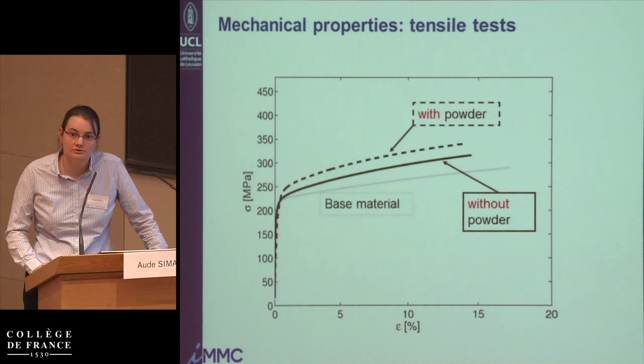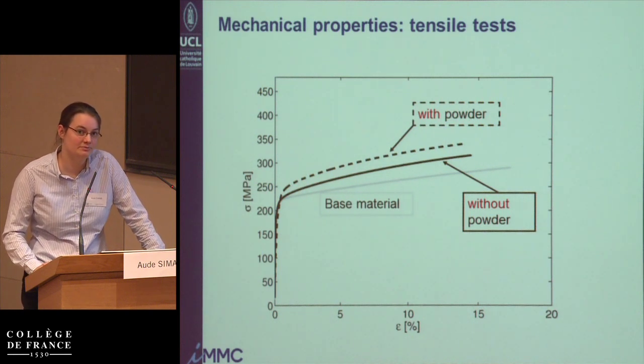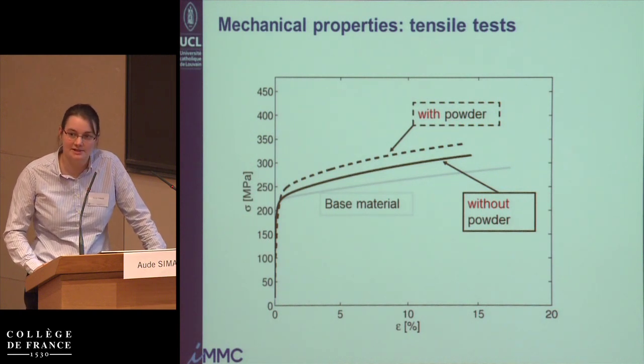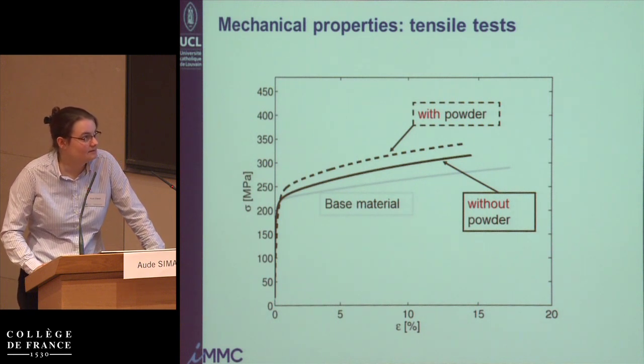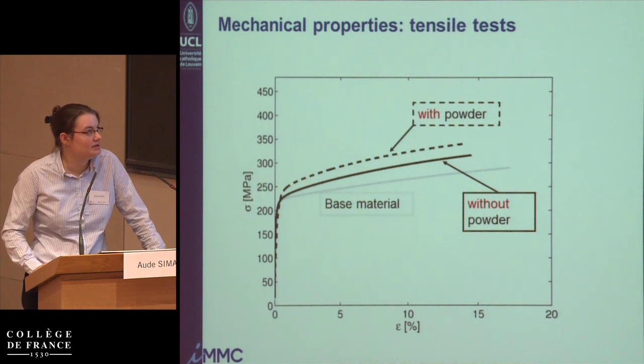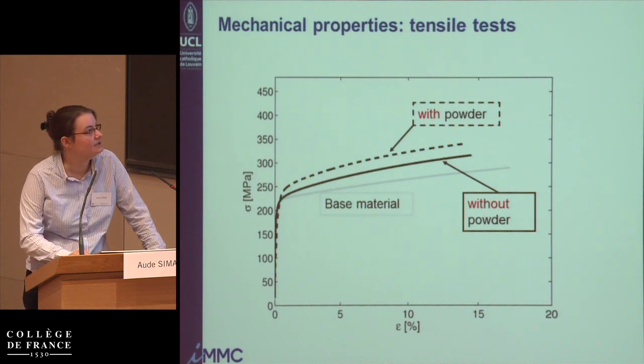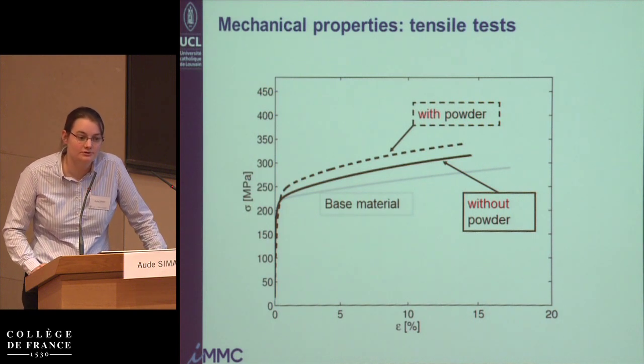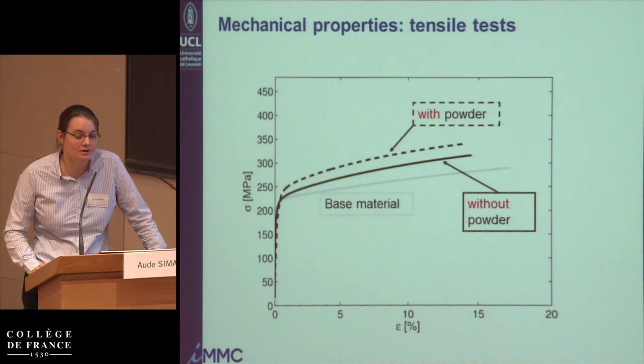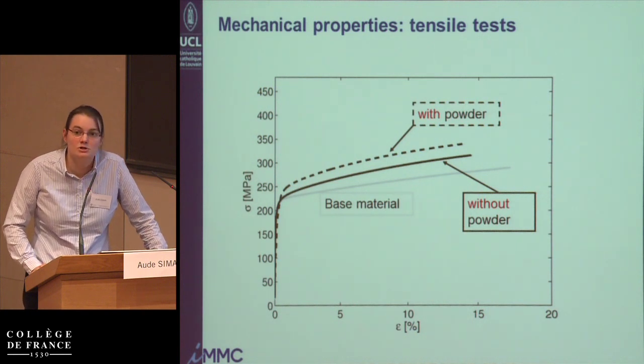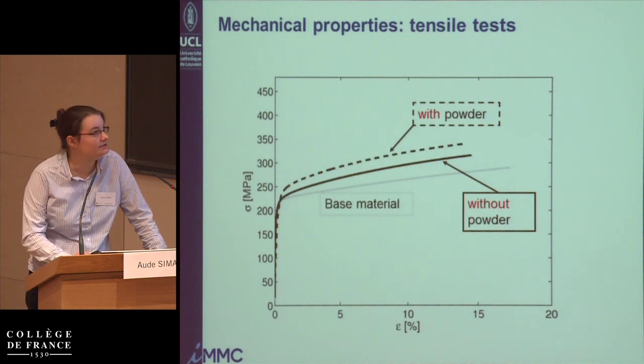And that is due to the smaller grains that you already obtained by friction stir processing. So it's interesting to already do some friction stir processing on the material without even considering making it a metal matrix composite. And with the yttrium powder, you even have a higher strength and higher strain hardening ability. But as I told you before, the very low volume fraction of oxide particles that were inserted in this material actually give you not that satisfactory results in terms of improvement of the mechanical properties, but we still have an effect, and it's very reproducible.